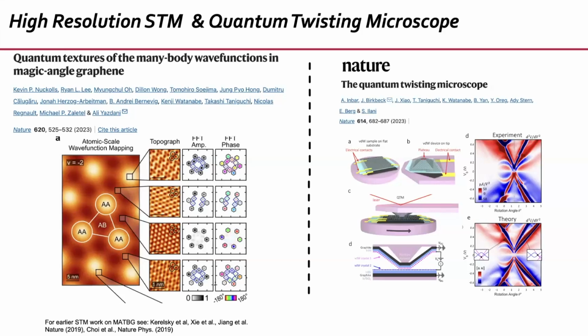For example, they could do something which is effectively ARPES, angle resolved photoemission spectroscopy, of the electronic structure of twisted bilayer graphene. This is what I'm showing here, but they're doing this with 2 to 3 orders of magnitude higher energy resolution than actual ARPES. And you can do this in the presence of a magnetic field. You can vary temperature a lot, etc. And you can actually scan and do all of this locally. So this is a very interesting development.